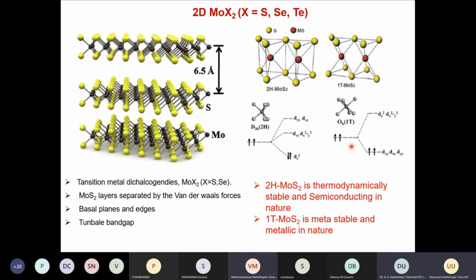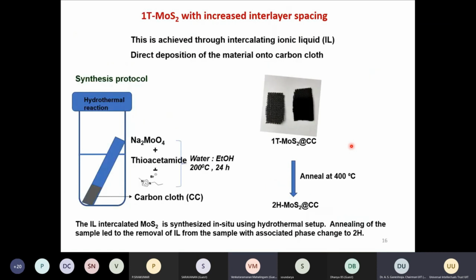particularly in colloidal synthesis. If you make a thin film of MoS2, then you can prepare pure 1T phase material, which has several applications, for example in field effect transistors, and they are also very good materials for the hydrogen evolution reaction. They have shown excellent activity for thin film based material. However, in the colloidal synthesis, it is very difficult and challenging to prepare. So that's why we wanted to see whether we can make the 1T phase.